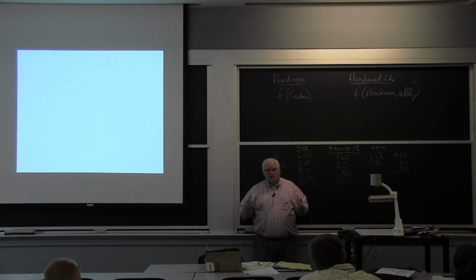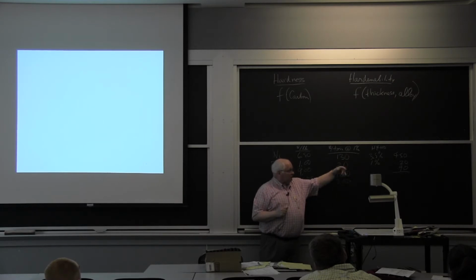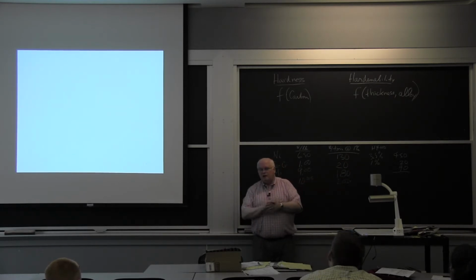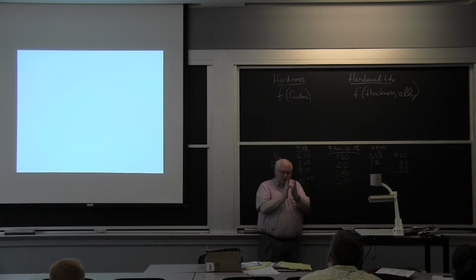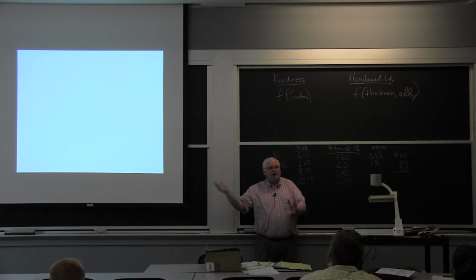In fact, when they redid the Seawolf in the early 90s, the problem with the Seawolf is they were using HY100, which is this composition. I wrote down HY100, same as HY80, just tempered at a lower temperature to retain a little more strength. But the weld metal was on the high side. All the alloying elements, you have a range for each alloying element. The carbon might be between 0.08 and 0.16. Well, what did they have for the carbon? It was 0.15.